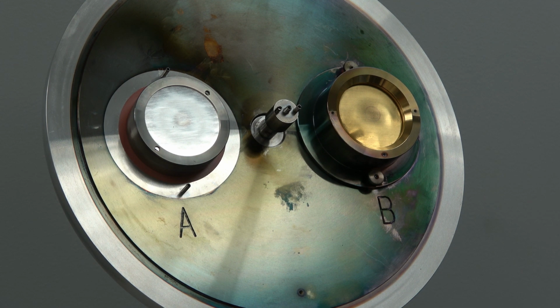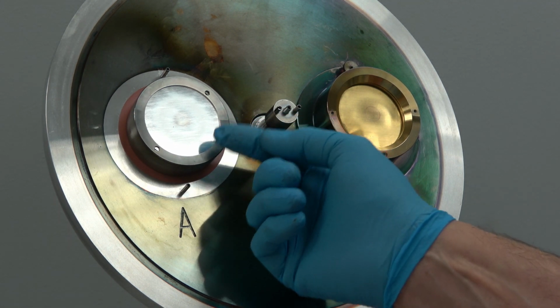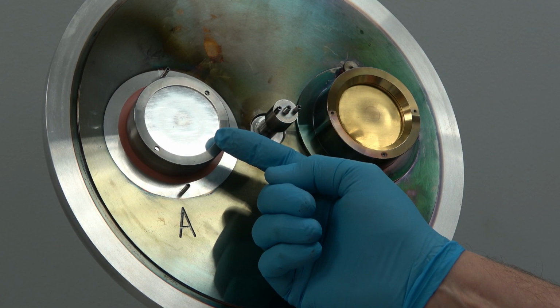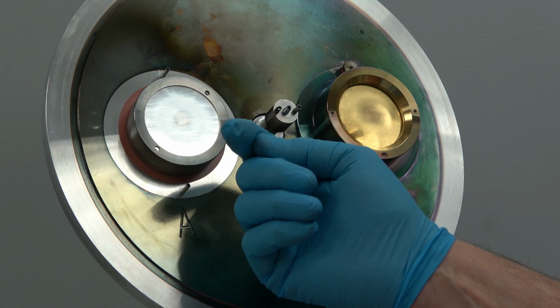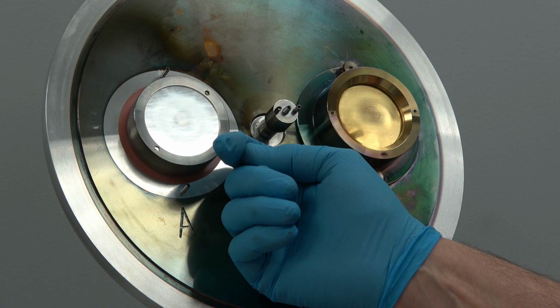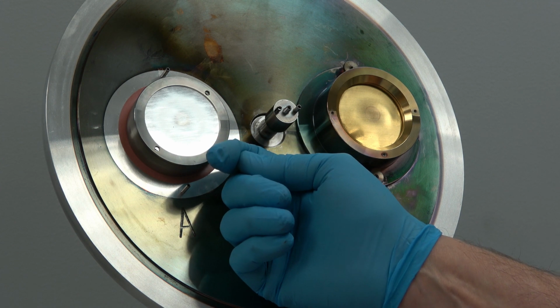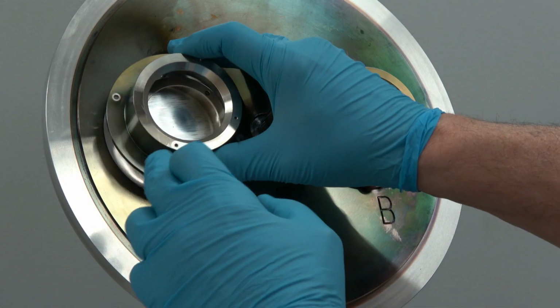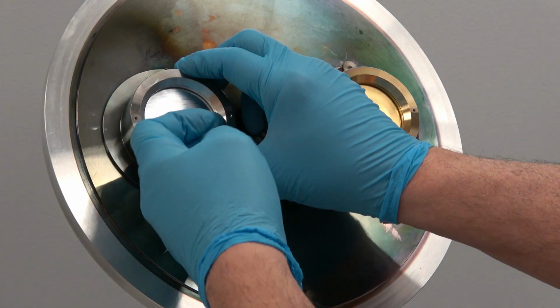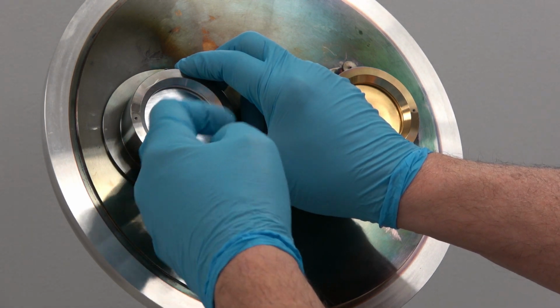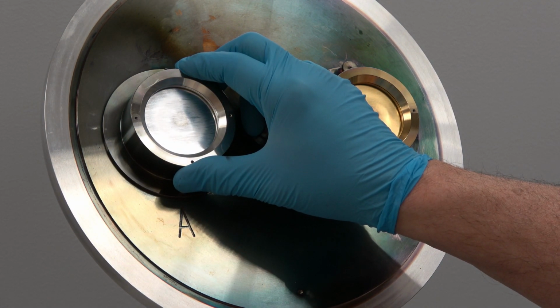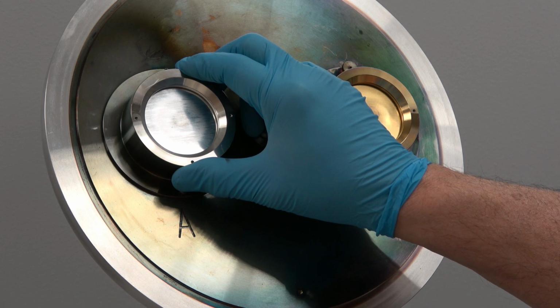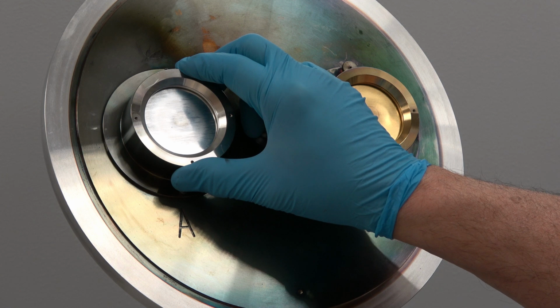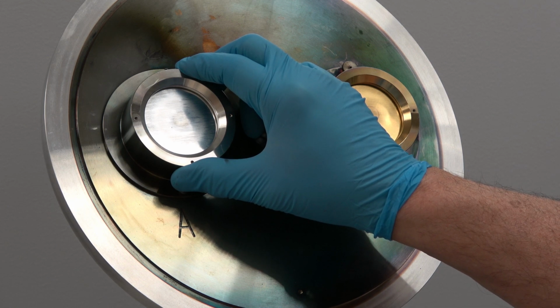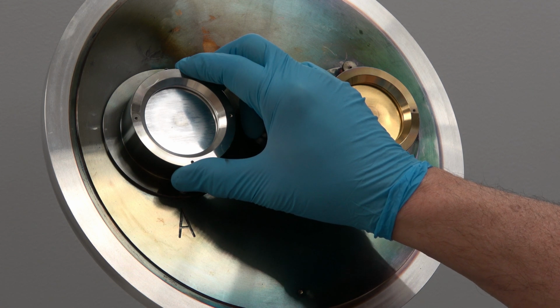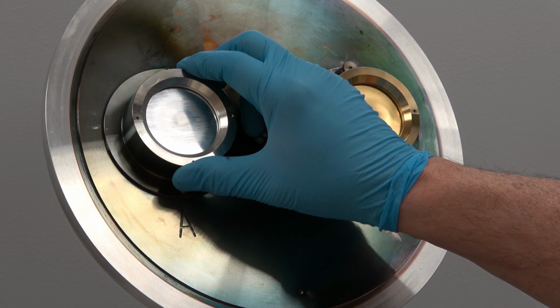Now, if we add a thicker target, the target retaining ring moves forward, let's say a half millimeter, because you have a 0.5 millimeter target. So that closes the gap between the dark space ring and the target retaining ring. If you have a too thick of a target and you don't use a spacer, you'll short out the target retaining ring to the dark space ring, and the system will tell you that there's a short in the sputter head, and you'll be scratching your head why.